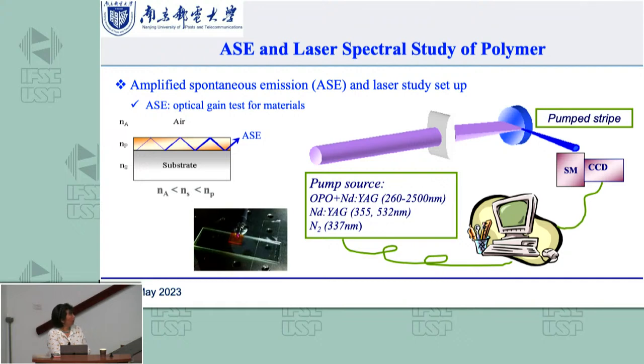laser. It uses a cylindrical lens to focus it as a strip on the sample. Then you put a detector at this edge. If ASE, that is amplified spontaneous emission, happens, you will detect it from here. That is, you can see the peak become narrow. So the real setup is like here. We use a red material and a focusing lens on the top. The detector is in here.